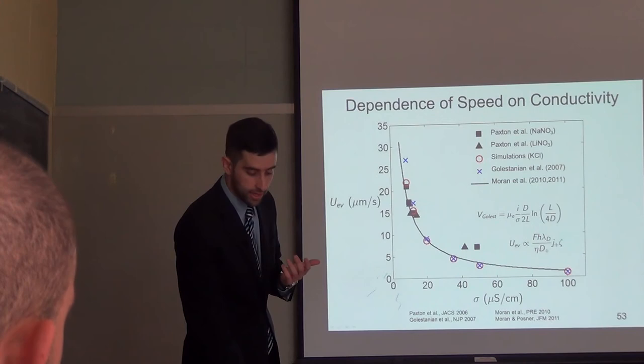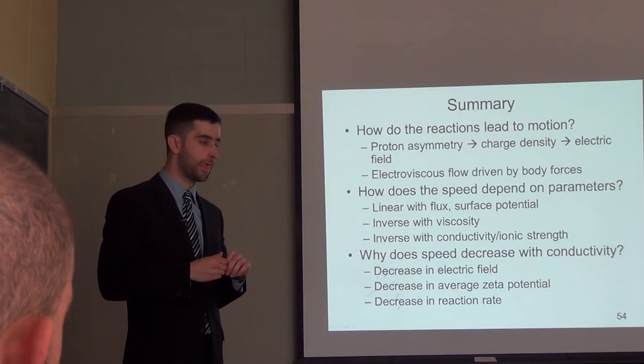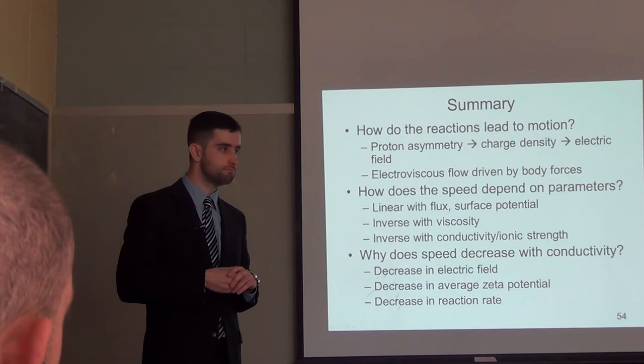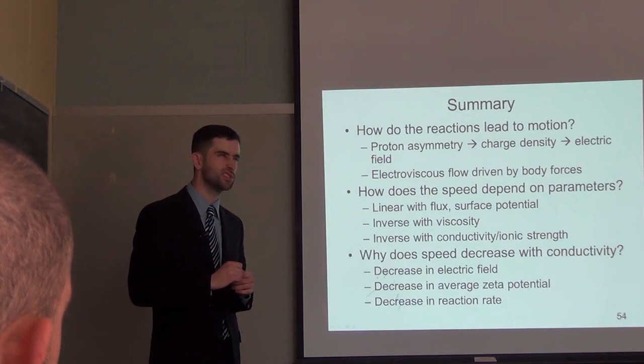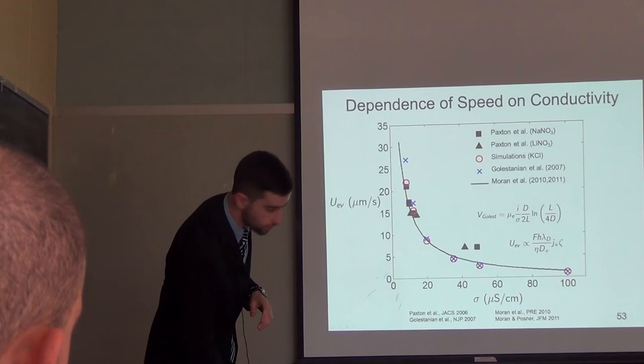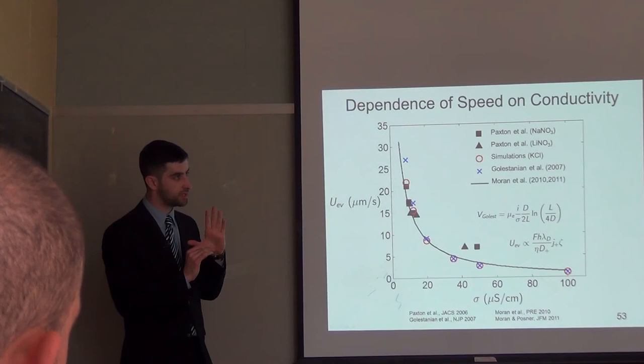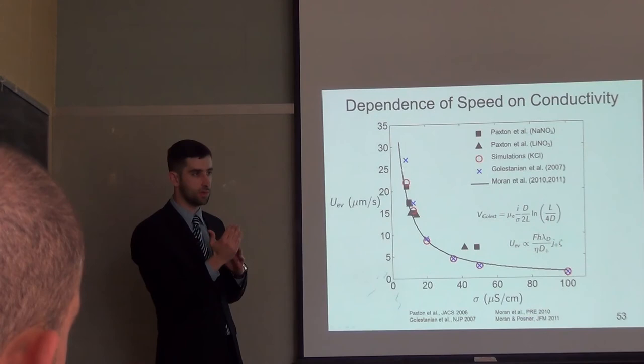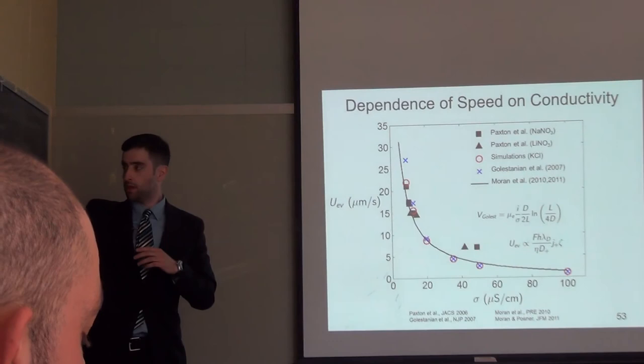We did look at the surface concentration of protons and it is slightly lower — on the order of about 70% of the value at the lowest conductivity. That's a relatively small decrease, but since we assume the reaction rate depends quadratically on proton concentration, that decrease gets magnified.